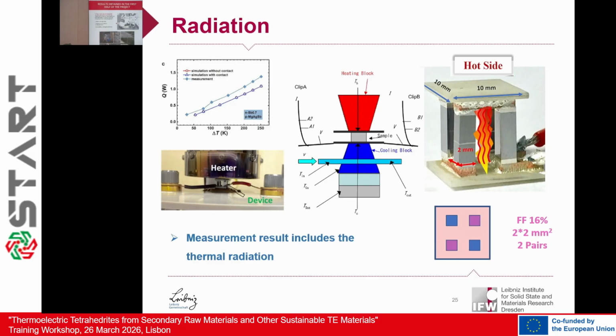We also figured out, with the earlier stage, that we in principle had a rather small filling factor, about 16%, for example. So there are some radiative heat losses. And when we improve, for example, the filling factor, going from 16% up to 64%, so 4 times higher, we can significantly improve the device.